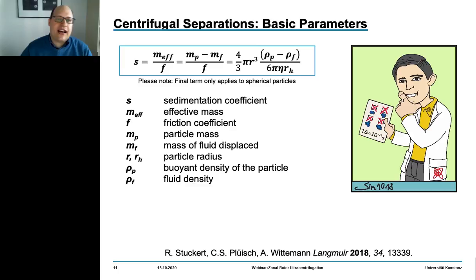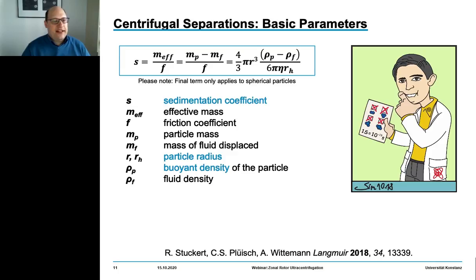Let's start with some basic considerations. If exposed to a centrifugal field, particles sediment at a rate defined by the sedimentation coefficient. The sedimentation coefficient is defined as the ratio of the effective mass of the particles to its friction coefficient, which also depends on particle shape.